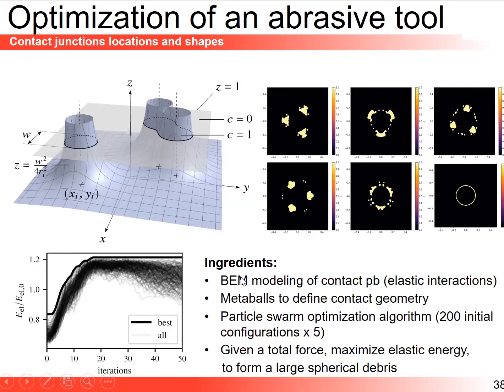So the ingredients of this paper, which had just been submitted yesterday, it's on Archive: we are using BEM modeling of a contact problem for elastic interactions. We use metaballs to define the contact geometry. So metaballs have those simple circular domains that define the contact regions. When field C is equal to 1, we're in contact. When C equals 0, we're out of contact. And we can merge those metaballs very easily. There are two metaballs that are making a more complex geometry,